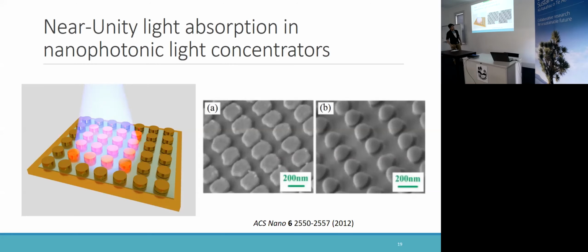We take a closer look. Here's the area without illumination, and here's the area after illumination. You can see that the shape is completely modified, which means the absorbed light energy has been absorbed by the nanoparticles and then converted to heat, melting the nanoparticles. Gold actually has a very high melting point, but in this case we can highly concentrate light energy and convert it to heat, and then melt the nanoparticle.